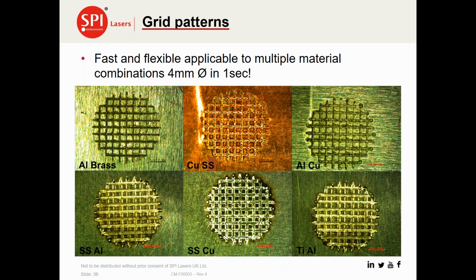Here are some examples of large area cross-hatching, where we've employed this on multiple materials. For example, aluminium to brass, copper to stainless, aluminium to copper, stainless to aluminium, stainless to copper, and even titanium to aluminium. This is showing we could create 4mm diameter weld sections in around 1 second process time. So it's a pretty quick process.